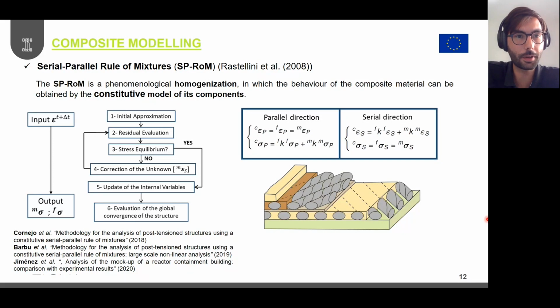In this case, for example, the serial parallel rule of mixtures, initially developed in 2008. And basically, this, let's say, constitutive law for composite modeling is mainly used for materials like the one depicted in this schematic figure. So we can see several layers. It can be formed by several layers, and some of them with oriented fibers embedded in some kind of resin or matrix material. And we try to fulfill mathematically several equations at once that can be seen in the parallel and serial directions at the top of the figure.